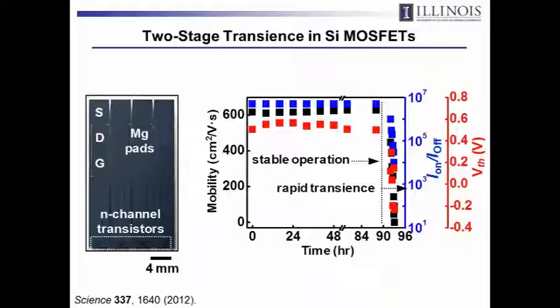So there's an array of transistors down here encapsulated. And what you see is these are various performance metrics, mobility, on-off current, and threshold voltage. You monitor those over time. And what you see is very stable, rock-solid operation up until the time when the encapsulating layers are now dissolved away. At that point, the silicon and the magnesium starts to dissolve because they're exposed directly to the water, and then you have a rapid, catastrophic degradation in the electrical properties.